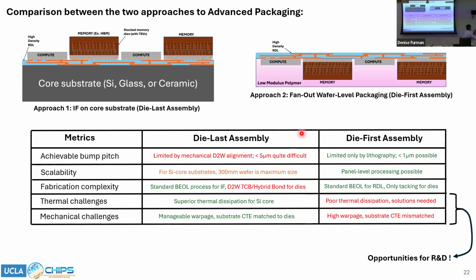So now let me compare these two approaches, approach 1 and approach 2. Approach 1, however, does have some issues, especially when you want to push the pitches even finer. And that is where I think approach 2 can be used to build future HPC systems, which will be the main focus of the remainder of the talk. So why is that the case? In approach 1, the achievable bump pitch involves a mechanical process at the end, because you have to pick up the die, align it, and bond it to the substrate. So getting less than 5 micron bump pitch is quite difficult. However, in the fan-out process, the dies are already embedded in a molding compound and the interconnects are created lithographically. So you're only limited by lithography, and you can even go sub-micron.